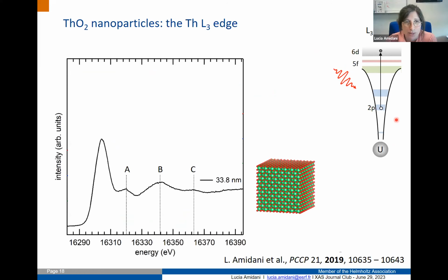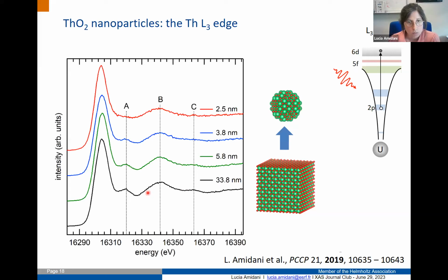So actually we wanted to bring some contribution to this more structural understanding of nanoparticles. Our work started with the thorium L3 edge. I joined the group, and those measurements were taken, and we see that at the L3 edge, the big nanoparticles like bulk have this nice spectrum. As soon as we start to decrease the size, maybe already at 3.8, but especially at 2.5...